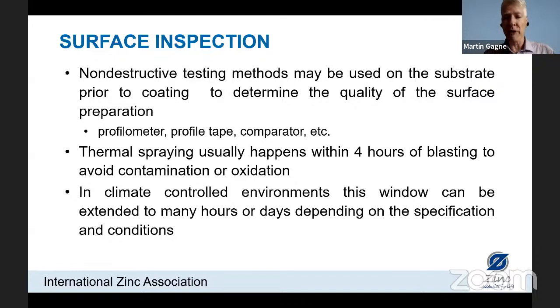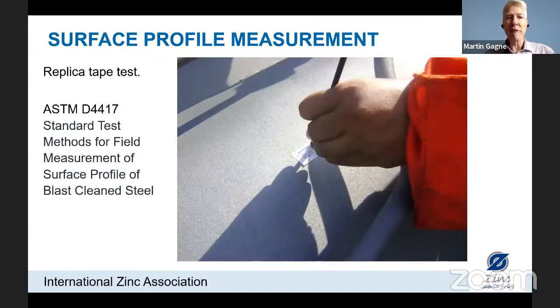Mostly this is in a shop environment, although there has been very good field containment where we are able to extend the time from blasting to spraying for whatever reason. But for surface profile measurement, there is an ASTM tape test D4417. This is a standard test method for field measurement of surface profile on blast clean steel, very specific to the application. We put a tape on the surface, we burnish it so that it takes on the profile, and then we can measure the profile on the tape.